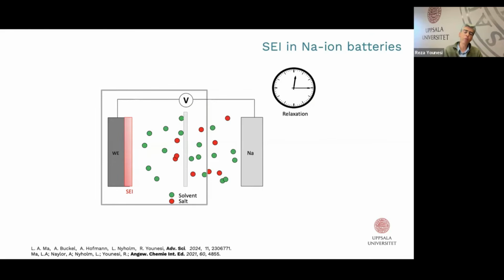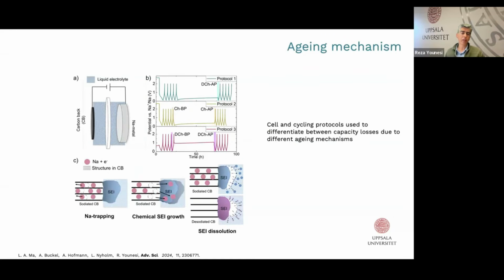So by having this blocking membrane, we try to block any crosstalk between the electrodes. On the left, you see the schematic picture of the cells we have been using. On the right, you see different electrochemical protocols we use to mimic different aging in batteries. For example, on top, the cell was cycled a few times, then stopped at almost 0.1 volt, a very low voltage, where SEI had already formed. By keeping the cell at that potential for an extended time with no external current or potential, we make sure the electrode is at low potential.